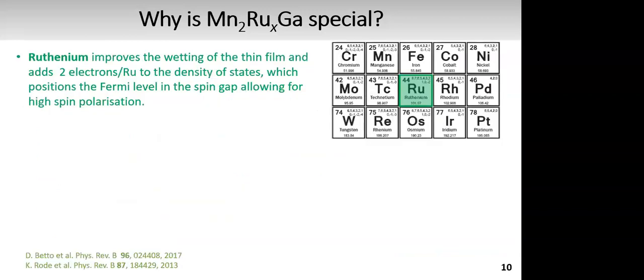Then we have ruthenium, and ruthenium has two important roles for MRG. It improves the wetting of the thin film onto the MgO, and it also adds 2 electrons per ruthenium to the density of states, which helps position the Fermi level in the spin gap. Hence, we can have high spin polarization.